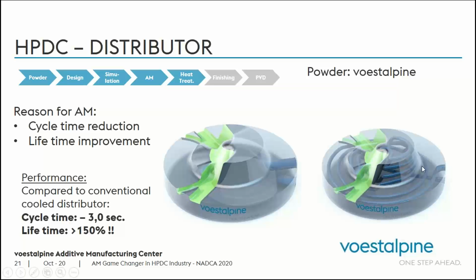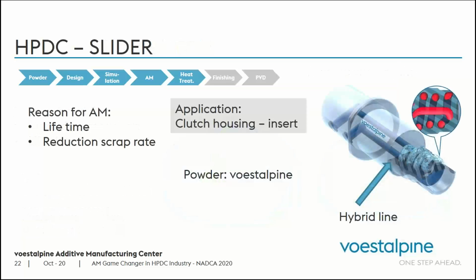And if you look on the right hand side here on the picture, you see how complex is the shape of the cooling channel. You're able to get it closer to the surface with engineered in and out flow of the cooling. And the lifetime was improved by 150%. So here, literally, you're talking about a huge improvement. It's not just evolution, but this is revolutionary in having a main improvement on your performance of the high pressure die casting application.